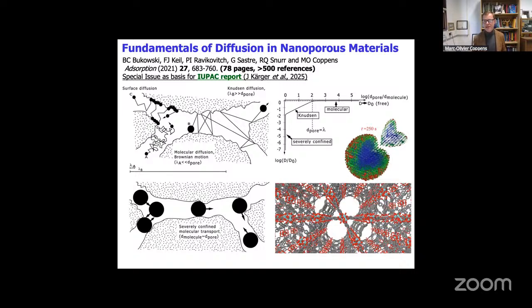So both the topology, as I highlighted, and the morphology can play a role. If a catalyst is deactivating over time, right? So this is just an image here on the right, just a snapshot of a simulation, but over time, what is accessible of the inside of that pore space will change, right? And this is something really difficult. It's much harder to test experimentally. There's more and more insight now with molecular probes going into porous materials, but the majority of the work is still on zeolites, and maybe some on MOFs, microporous materials.